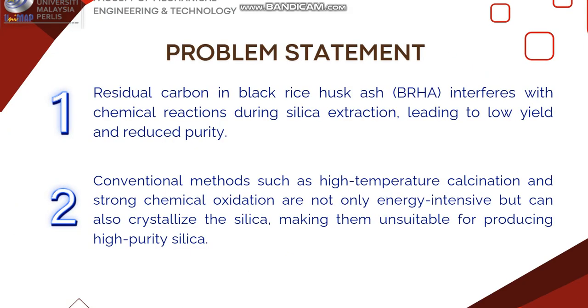The problem statement. The residual carbon in BRHA interferes with the chemical reaction during silica extraction, which leads to low yield and poor purity. Conventional methods like high temperature calcination are energy intensive and can cause silica to crystallize, making it unsuitable for producing amorphous high purity silica. Our study focuses on addressing this issue through an optimized chemical extraction process.